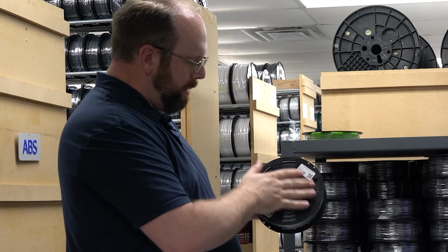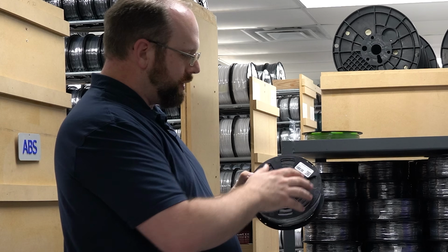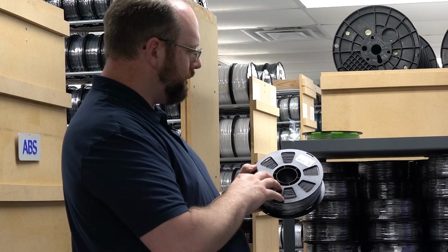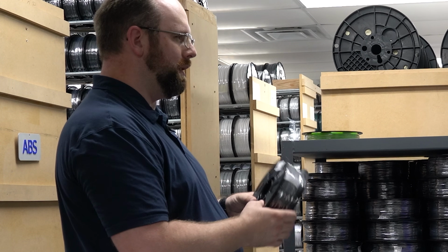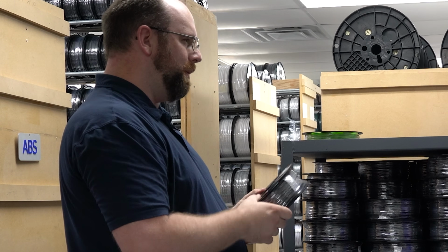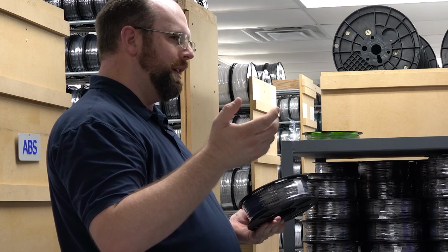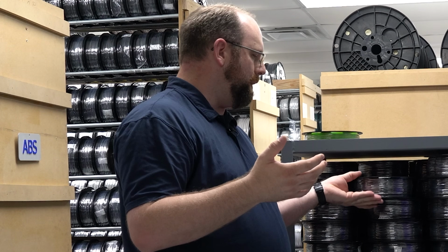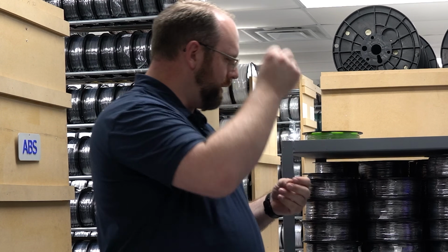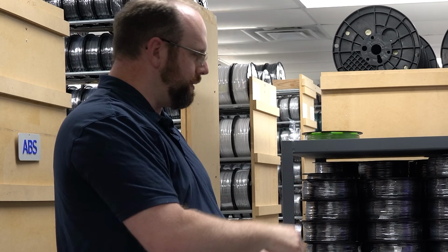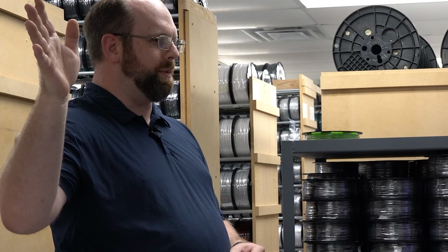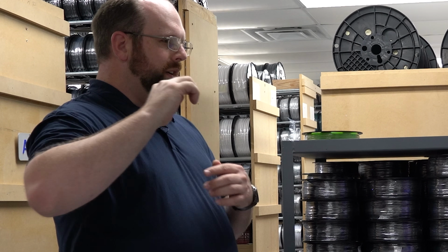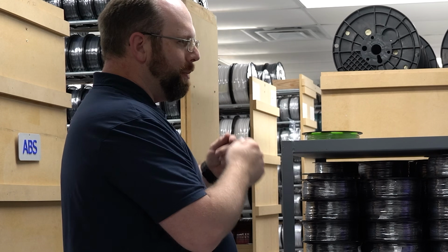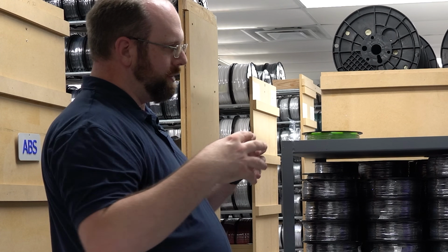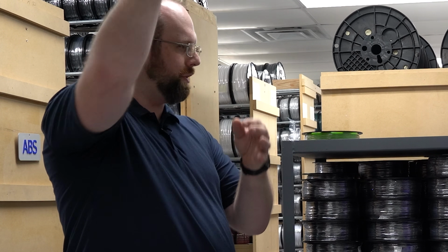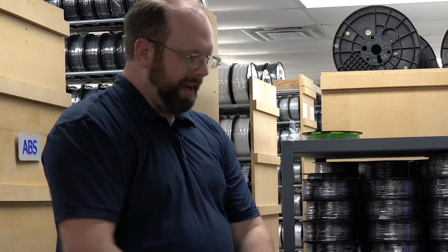So a lot of that moisture that might be on the surface from humidity, the hygroscopic action, if you will, would actually cook off pretty soon after it gets heated, before it even gets liquefied. And it certainly wouldn't necessarily get mixed into the filament, because there's no screw involved stirring it in like we have over there. That's part of the problem with moisture on the resin: it gets stirred up inside the polymer and mixed all throughout the polymer when it goes through the screw. Whereas a 3D printer, it's laminar. It just goes straight through. The outside's the outside, and it comes out.